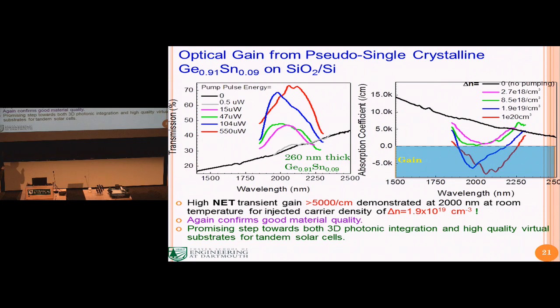So this black curve is without pumping, measured by a regular IR spectrometer. And we start to do the pumping at low level. It converges with that data pretty well, except there's a slight increase in transmittance here. As you keep on increasing the pumping energy, you can see the transmittance near 2 micron increasing from about 30% all the way to 70%. So the material gets a lot more transparent.